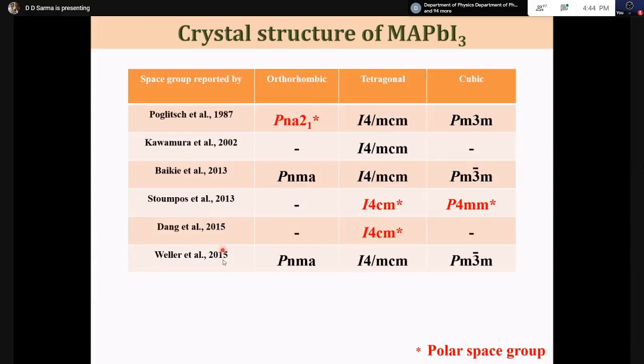Starting from 1987 to 2015, everybody was talking about the same compound, MAPbI3. Three different phases, I told you: the low temperature orthorhombic phase, the room temperature tetragonal phase, and the high temperature cubic phase. And different symmetries, space groups, are written down here that were concluded by different workers. We don't have to pay too much attention except for the color coding. Whenever the color is red, that claims to be a polar structure, and whenever the color is black, it's a non-polar structure. This has centrosymmetry, and that does not have centrosymmetry.